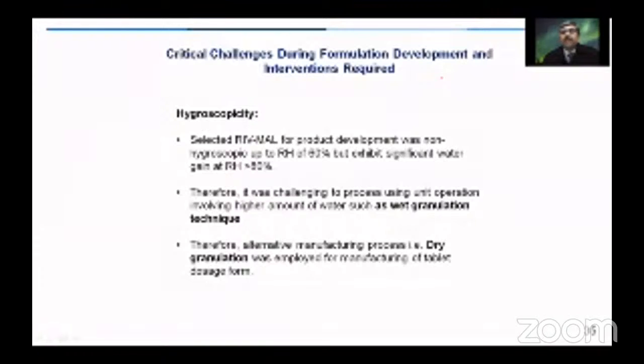Critical challenge that was identified for formulation development and the subsequent interventions that were decided was hygroscopicity, because we have chosen the co-crystal with the malonic acid as the optimal candidate for formulation of the tablets. But we know from our hygroscopicity studies that this co-crystal was much more hygroscopic as compared to the API. Therefore, it was challenging to process this using unit operation involving higher amount of water, such as wet granulation technique. And that is why we had to proceed with alternate manufacturing processes like dry granulation or the direct compression process.